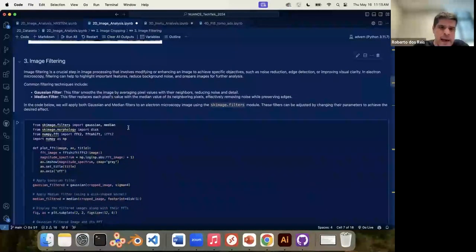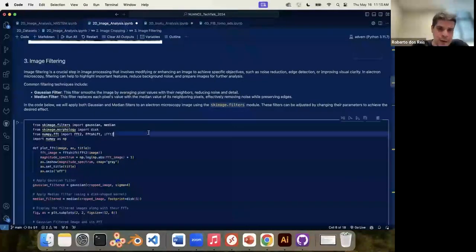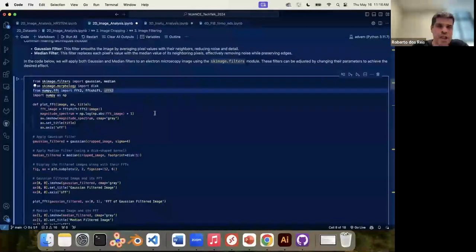They can do a simple filtering, right? So I added here a couple of filters. Those two are probably the most popular, the Gaussian filter and the median filter. You might see a lot of publications with those two applied. One thing that I really recommend is that anytime you apply those filters, mention on the paper that you did so, and add the weight of that. Say, if you apply a Gaussian filter with sigma equals 2, you just do that on the caption, right? And I will show you a couple of examples, by changing that number, how that changes